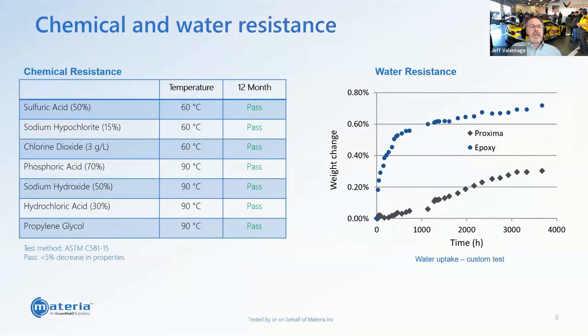Real quick, looking at chemical resistance. So this is looking at neat Proxima applications for chemical storage applications. You can see that it's very resistant to caustic type of materials. This customer was looking for this 12-month test at 60 degrees C. We were able to pass all the requirements looking at that application.